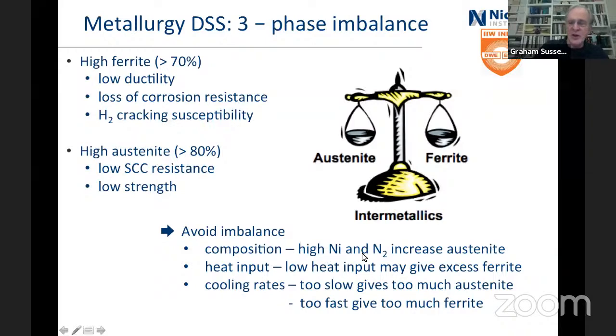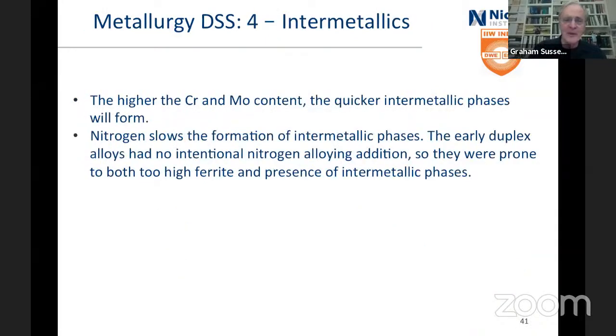So the composition, high nickel, high nitrogen increases the austenite, low heat input will give you excess ferrite. And if your cooling rate is very slow, you get too much austenite. And if it's too fast, you get too much ferrite. Have you ever thought that you're walking along a tightrope here? It's really quite tricky. But welders do it all the time. So the higher the chromium and moly content, the worse the intermetallic phases. The nitrogen slows it, I've said that earlier. And the earlier duplex had no intentional nitrogen, and so they were very prone to both high ferrite and the intermetallic phases.